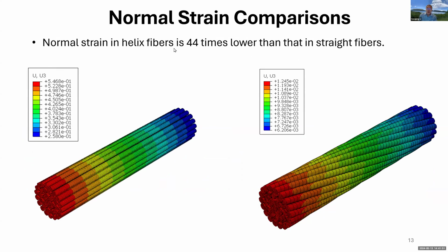And how about the principal strain? The principal strain of the helical fiber is about 44 times higher than the straight fibers. That means this fiber bundle will be able to deform more. Recall, our polymer can be deformed 10% before it fractures, and glass fiber in straight form 5%. So now, by just changing the configuration, you'll be able to increase the deformability so that the glass fiber bundle will be able to match the smart polymer. Hopefully they will work together to store more input energy.